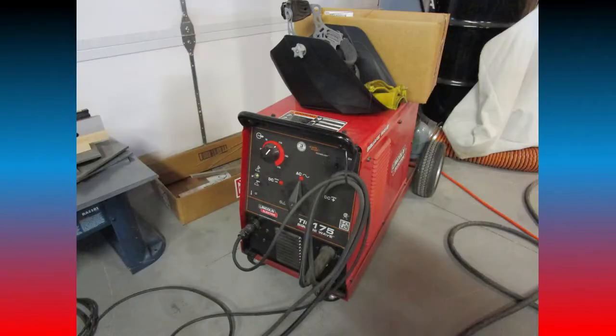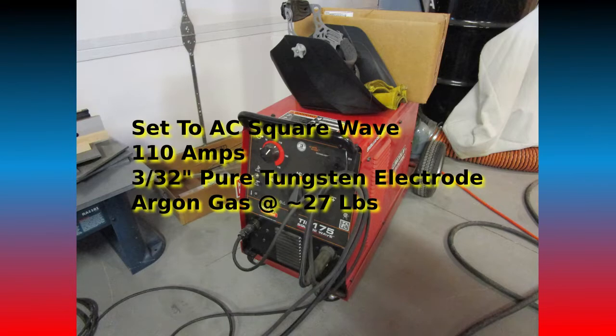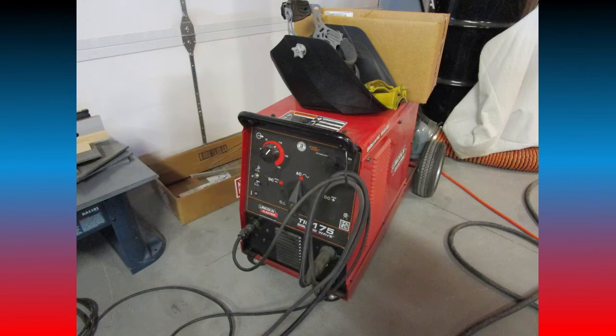The welder used for this project is a Lincoln Electric Square Wave TIG 175 as shown. You need a square wave to properly weld aluminum. This provides a cleaning action on the metal to remove oxides. Aluminum oxide has a much higher melting point than the base metal, making it a nuisance. The amperage is set to 110 amps for the 0.063-inch thick metal. Aluminum conducts heat away from the weld puddle quickly. Aluminum also produces a watery puddle, so you need to move the torch accordingly.